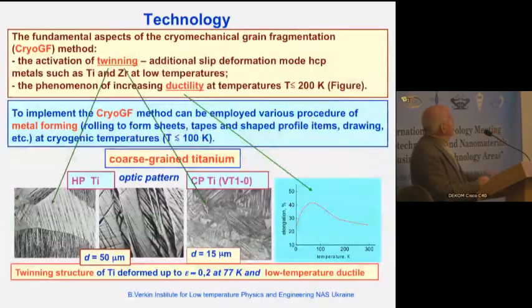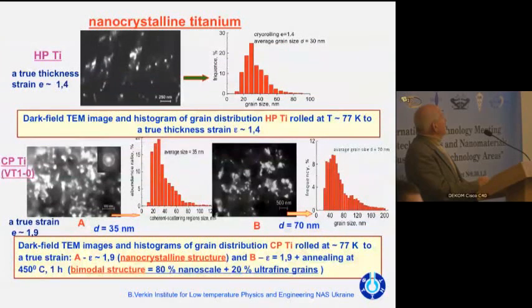Titanium is twinning at lower temperatures. At the bottom we have optical structures for titanium, and the initial size of the grain is 15 microns. Every grain is fragmented by twinning. This is the very mechanism. With the increase of plastic cryo deformation, the size of the grain decreases significantly. High purity titanium will have a grain size of 30 nanometers. Technical titanium has a larger grain size.